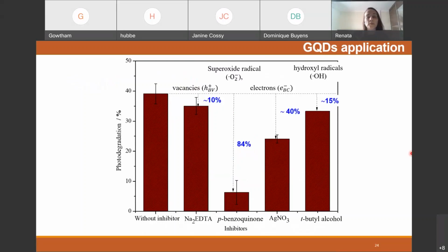We investigated the degradation process in the presence of inhibitors, for example, without inhibitor and in the presence of Na2EDTA. Na2EDTA inhibits the holes, because the quantum dots have photocatalyst properties, and the photocatalyst properties generate electron-hole pairs. In this process, it is possible to observe an inhibition of about 10%.